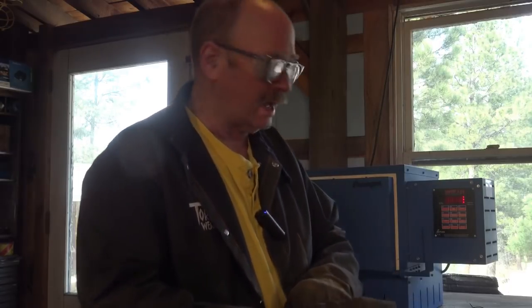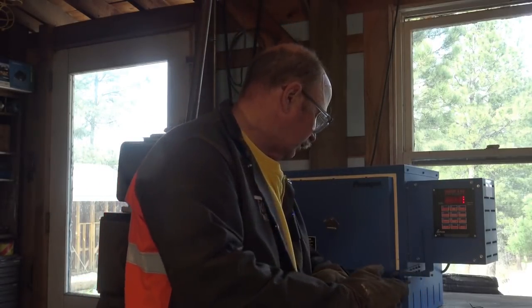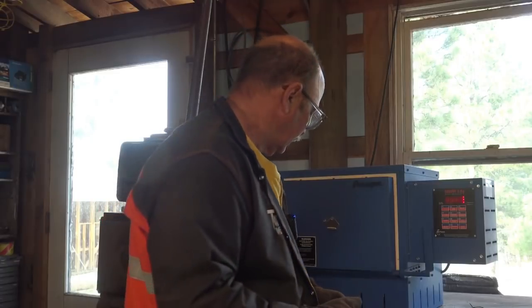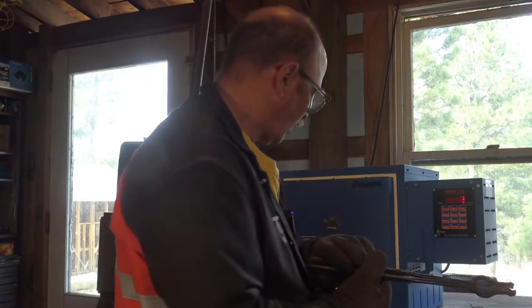Okay, I've let this piece soak for about 20 minutes at 1475, which again is the critical temperature for W1, not for 4140. But we're doing that just to see when it loses its magnetism. And also because this is a much heavier piece of steel. I haven't made a piece of 4140 that matches my other samples. So we're just giving it a fair trial here.